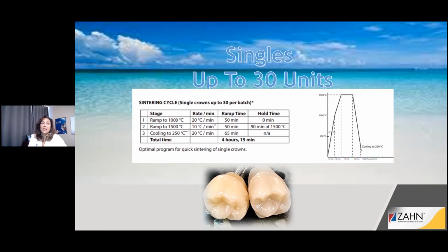And so it's a super simple program. Your 20C per minute to 1000 Celsius, and then 10C up to 1500. And then you're holding for 90 minutes. So this is the original IFU. And like we just talked about previously, that high temp is really up to you. As long as you're in that range of 1350 to 1550, you're good.